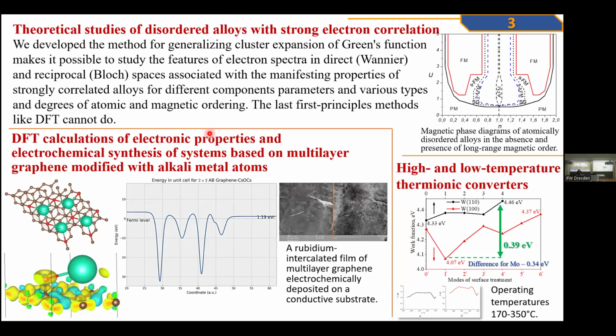The first thing I need to say about our investigation of quantum materials is the following. We developed a method for the generalization of the cluster expansion of the Green function, which makes it possible to study the features of electron spectra in direct and reciprocal spaces associated with the manifesting properties of strongly correlated alloys for different components, parameters, and various types and degrees of atomic and magnetic ordering. An arbitrary degree of ordering is inaccessible for first-principles methods like DFT. And we can do it.